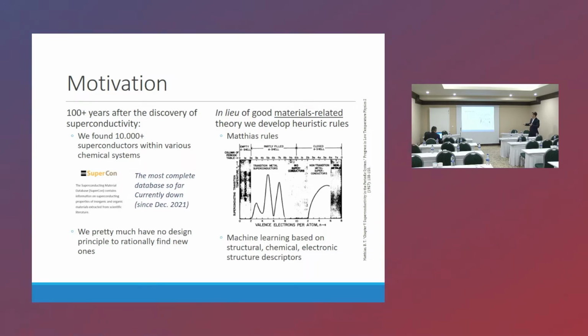So Matthias was a superconducting hunter in the 50s and 60s. He found superconductivity in a number, tens or hundreds, of different metallic alloys, and he was able to plot a Tc versus valence electron count relationship, and he found that actually superconductivity tends to be suppressed at opposite electron counts. We will come to that point in a minute.